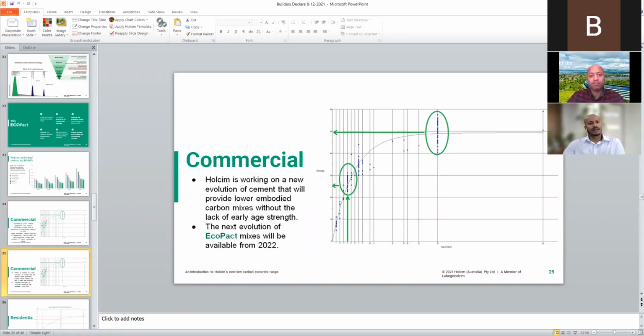I mentioned earlier that we're working on the next evolution of cementitious additives. This cementitious additive is going to be a game changer. It provides superior strength at early ages, such as 1 to 7 days, but at the same time, it provides very low shrinkage, which is of benefit in certain applications. So in 2022, mid or early 2022, we hope to have this commercialized and ready as an offering into the market.